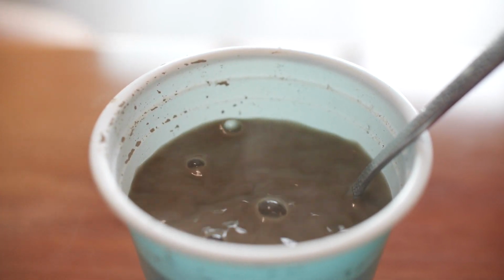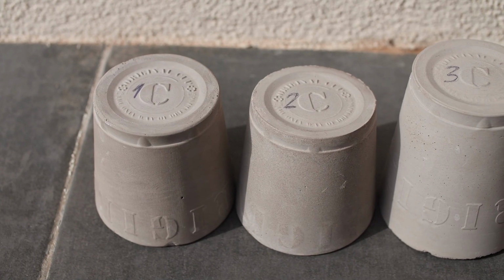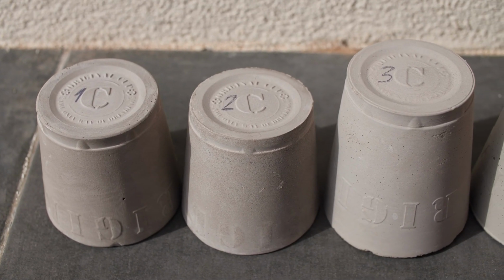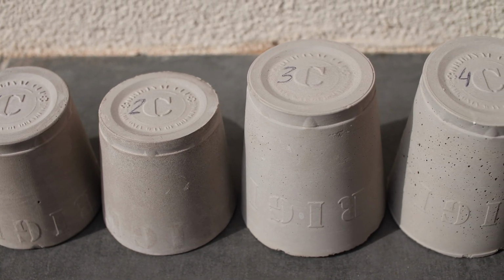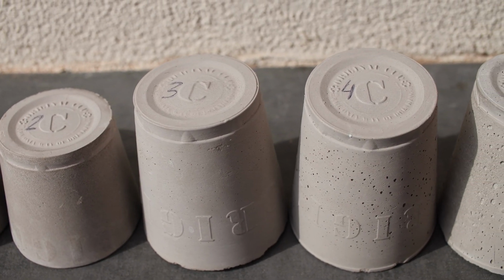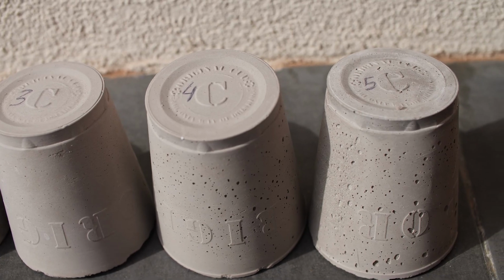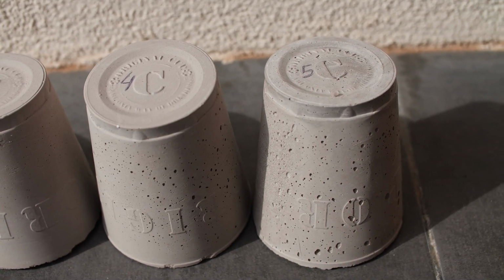A few weeks ago, we tested different mixtures with varying amounts of sand and found that a sample made with only cement and water, sample 1 on the left, yielded the best results with the fewest cavities.